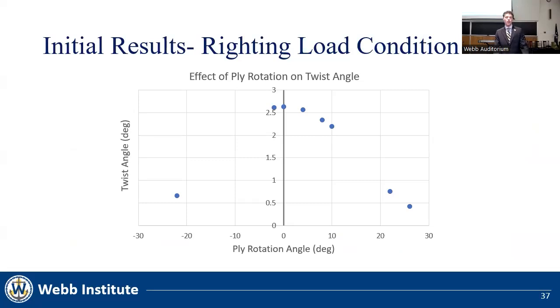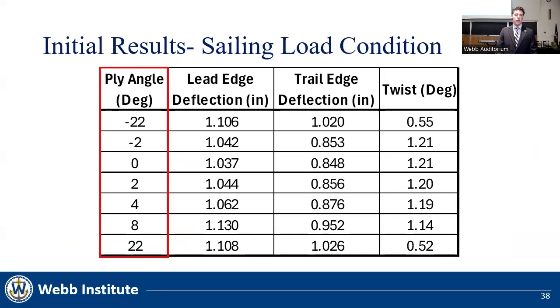Our initial results showed that a maximum twist angle was achieved in the righting load condition at 0 degrees of ply rotation angle, and that rotating the plies in either direction resulted in decreased twist. Here are the same results, but for the sailing load condition rather than the righting load condition. In the left column, you see the ply rotation angles. The middle column shows the leading and trailing edge deflections, and the final column shows a calculated twist. Again, a 0 degree ply rotation angle in our initial study resulted in the most twist.